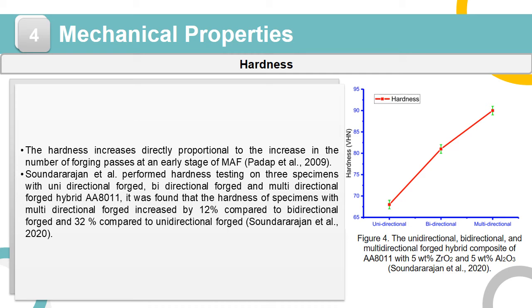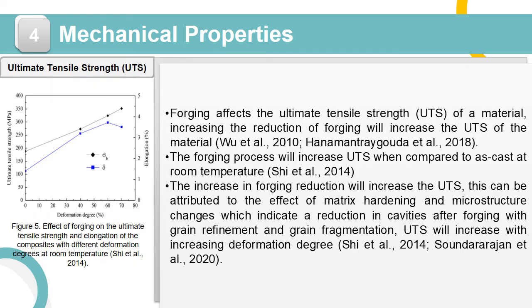According to research conducted by Soundararajan et al., hardness testing was performed on 3 specimens with unidirectional forge, bidirectional forge, and multidirectional forge. It was found that the hardness of specimens with multidirectional forge increased by 12% compared to bidirectional forge and 32% compared to unidirectional forge, as we can see in figure 4.